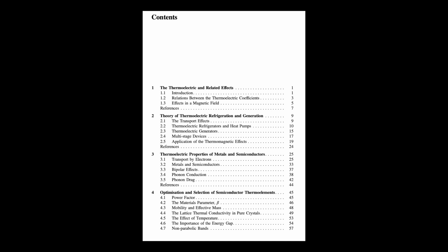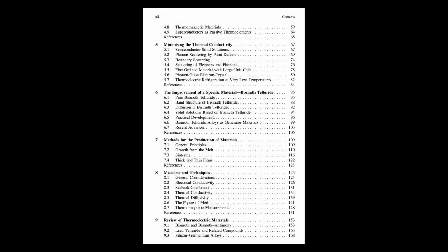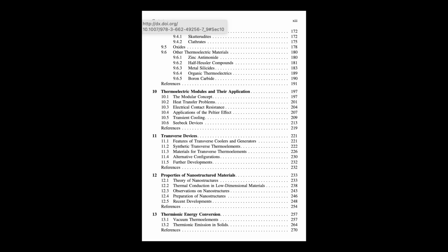A huge fraction of commercial thermoelectric modules today use these Bi-Te-based alloys for both cooling and power generation. So what have been the practical developments, getting optimal conductivity and ZT? Well, over the years, there's been steady improvement through better material growth, processing, and understanding. Researchers figured out the sweet spot for electrical conductivity to maximize the figure of merit. The ZT values for the best Bi-Te-based couples have climbed from maybe 0.6 in the early days, continually pushing higher towards and sometimes exceeding 1.0 through ongoing R&D.